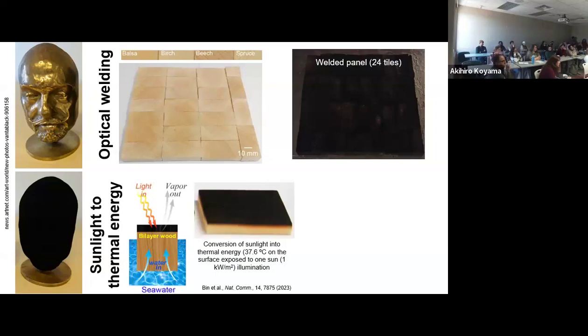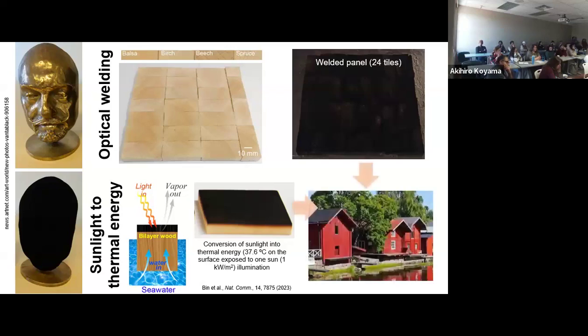One application of this was shown earlier, much earlier, but with typical carbonized wood. This is not super black. Super black would be much more efficient. But in this earlier work where wood was carbonized, it was possible to see how the material can be used in desalination and sunlight energy conversion, right? Because all the light is absorbed. This is heated locally, and then it can be used for that type of conversion. So very typical high-end material, but from the perspective of construction, you can realize that it can be used also in roofs to produce a quite interesting concept for cold areas, right?